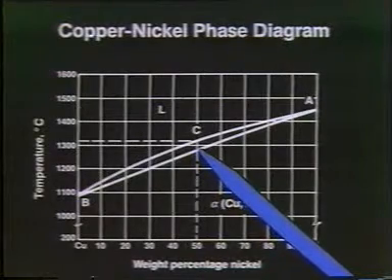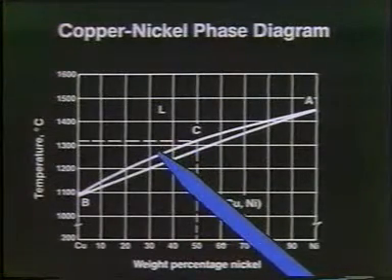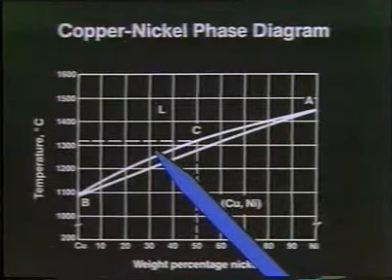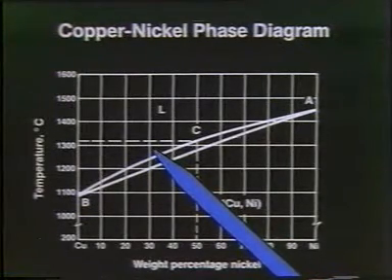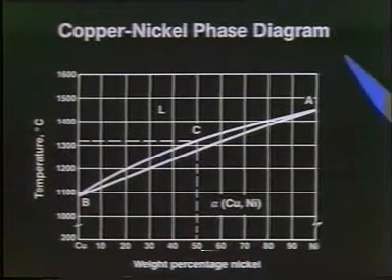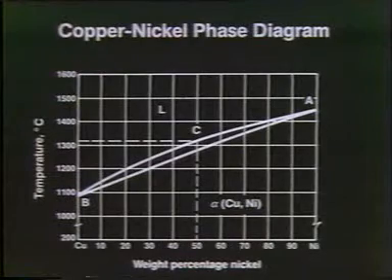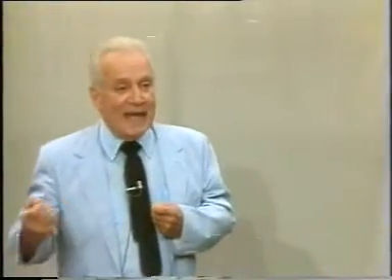Still lower, it will be here for the solid and way over here for the liquid. And so we move on this particular equilibrium diagram from one point to another just by solidifying, and inside of this bucket of metal we're segregating the material. We are causing the dendrite that is solidifying first, the little tree, to be one composition. The limbs and branches are going to be another composition. So when we're all through, we didn't decant the metal, but we can go back and etch the surface, and we look at that etched surface, and because it's different chemically, we see we have dendritic segregation.